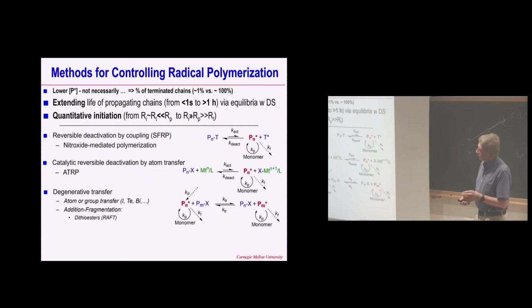Another very important issue is that you need to have a fast initiation because you would like to grow all chains at the same time. In a conventional radical process, you have a very slow initiation. Half-lifetime of initiator is 10 hours, which means that you have a so-called steady state in conventional process. As fast as you initiate, as fast you terminate. You want to terminate 1,000 times slower than propagation, therefore initiation should be also 1,000 times slower. So no control, no block copolymers, no stars, no bioconjugates, or any kind of organic-inorganic hybrids.